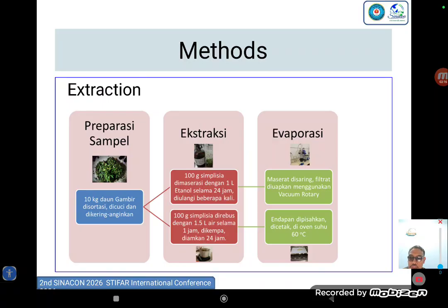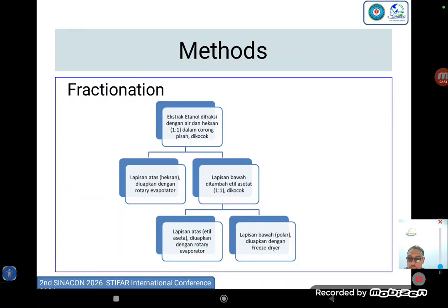First, extraction. Gambir leaves were obtained from Balitro, Solok, West Sumatra. The extraction process was carried out using two approaches: ethanol maceration and a traditional water boiling method. The fractionation process: the ethanolic extract underwent a sequential separation, resulting in three distinct fractions: N-hexane, ethyl acetate, and a polar fraction.